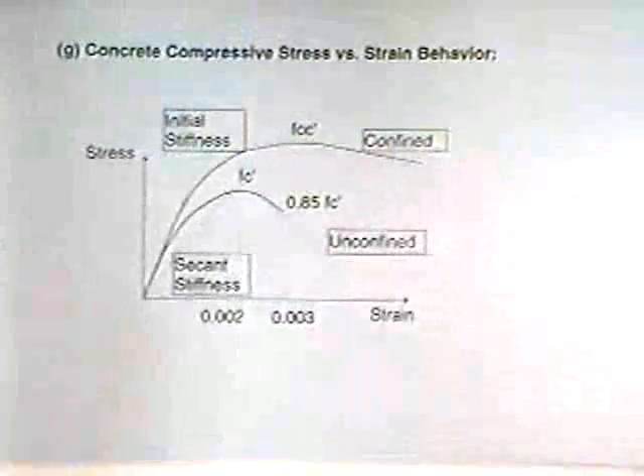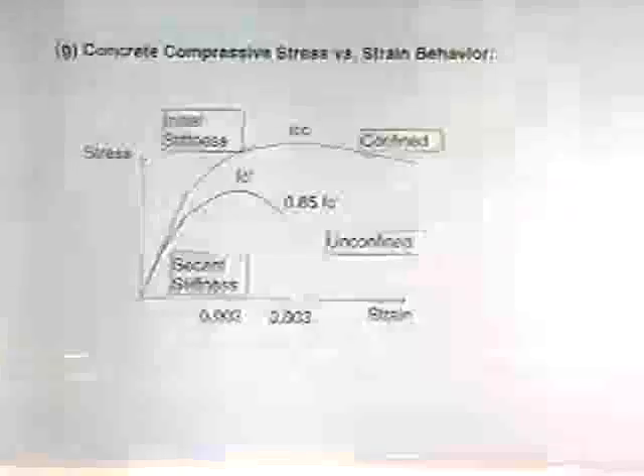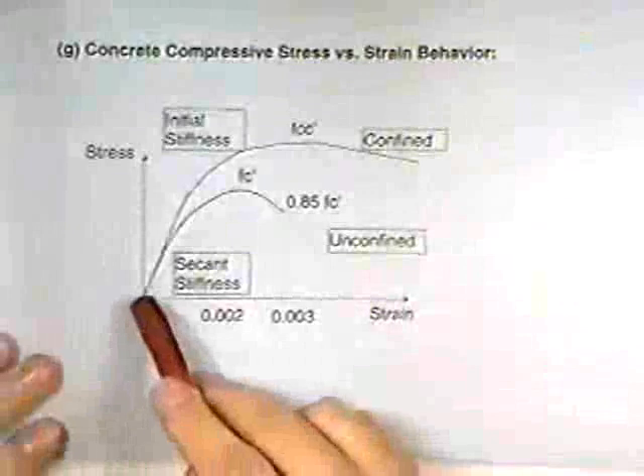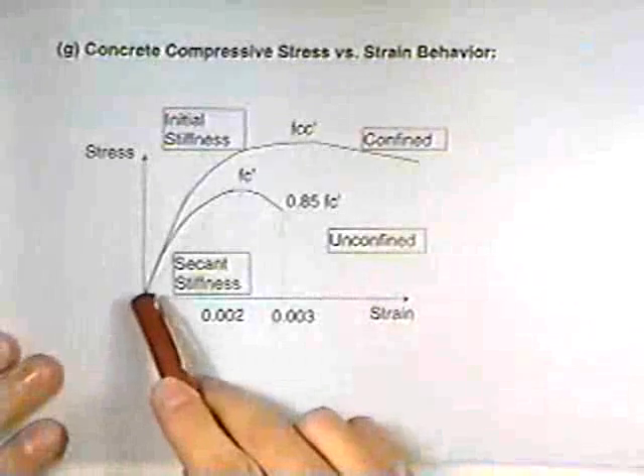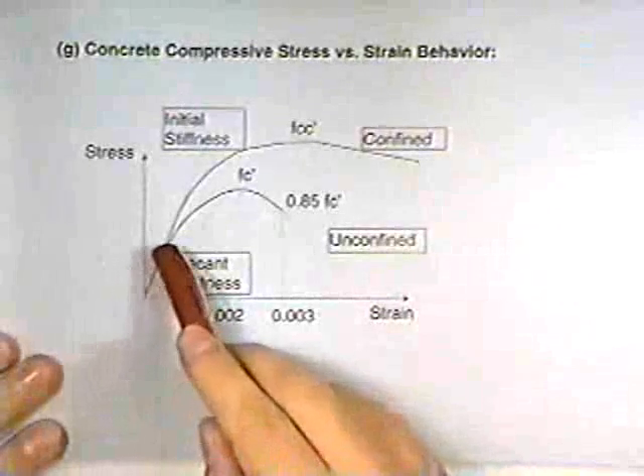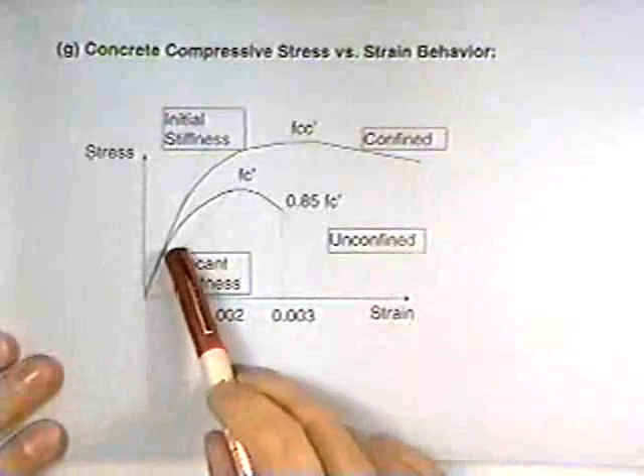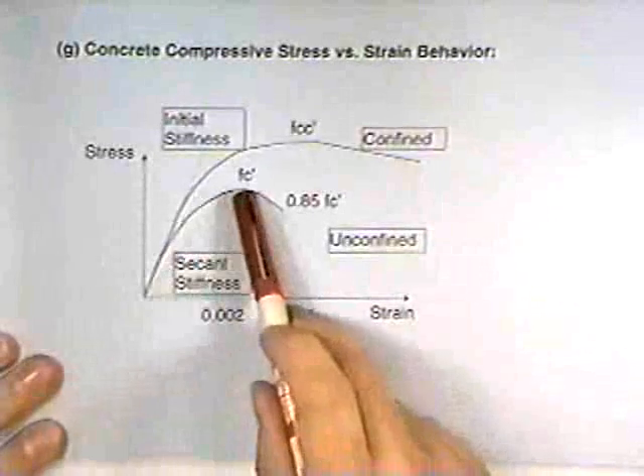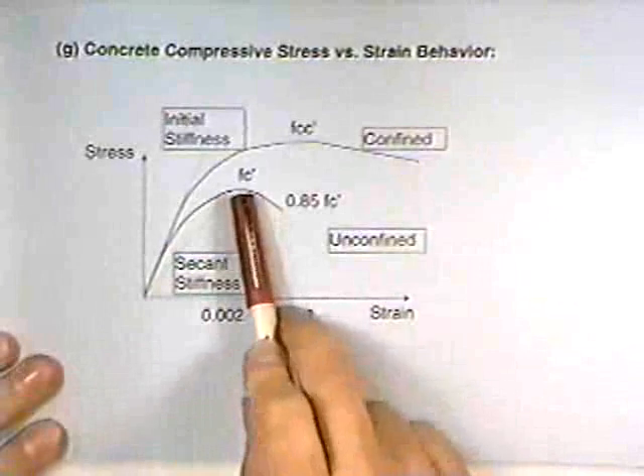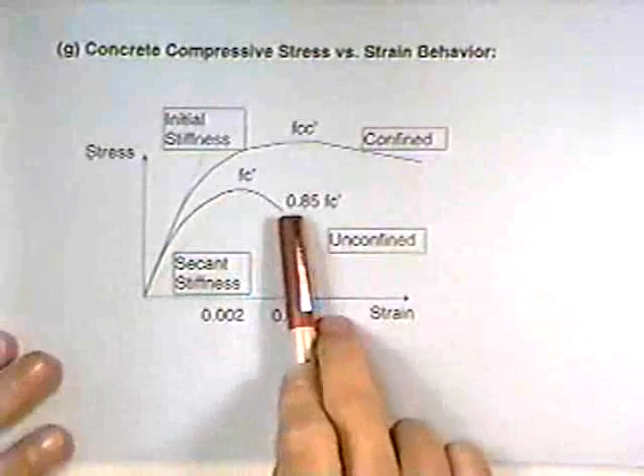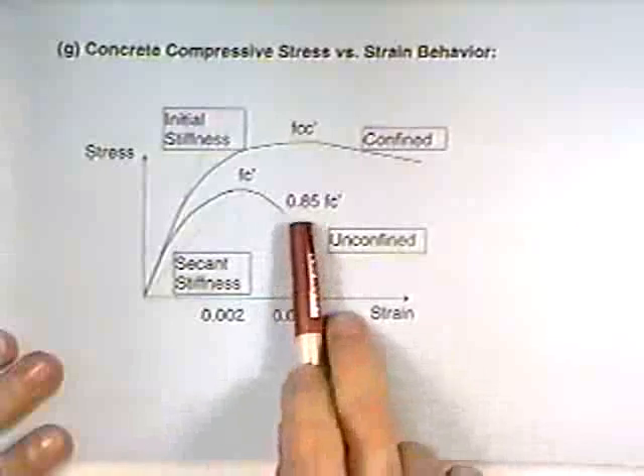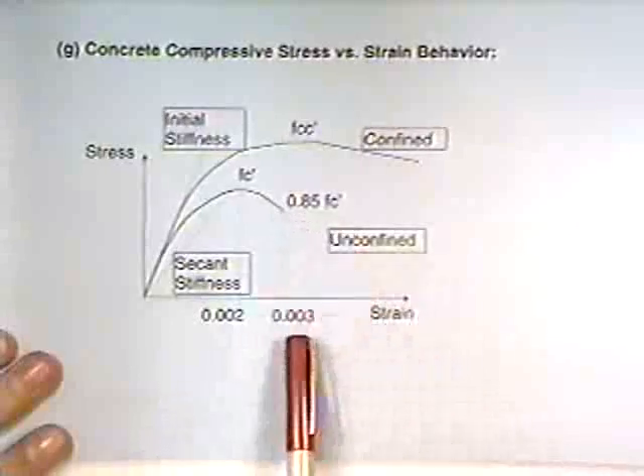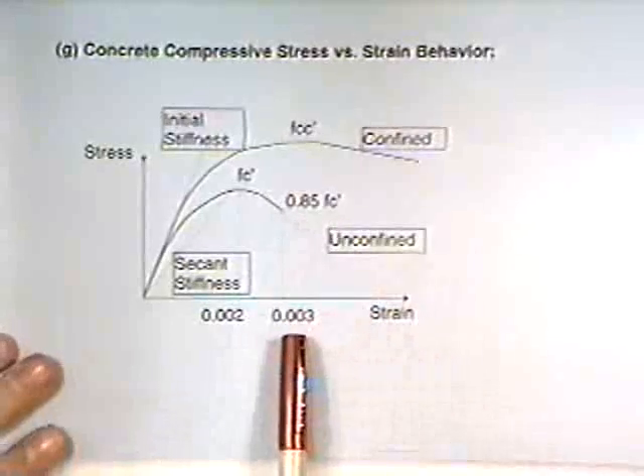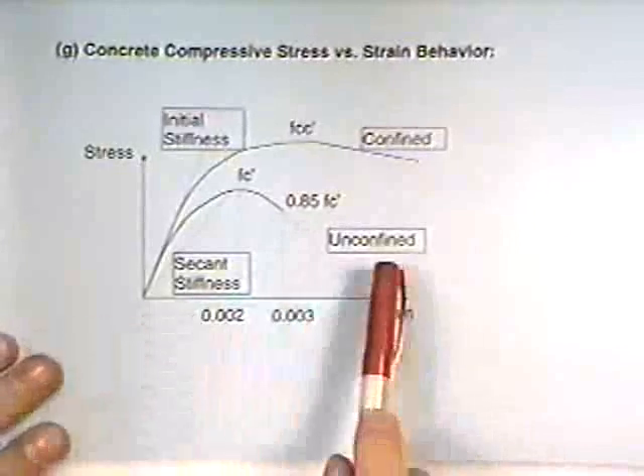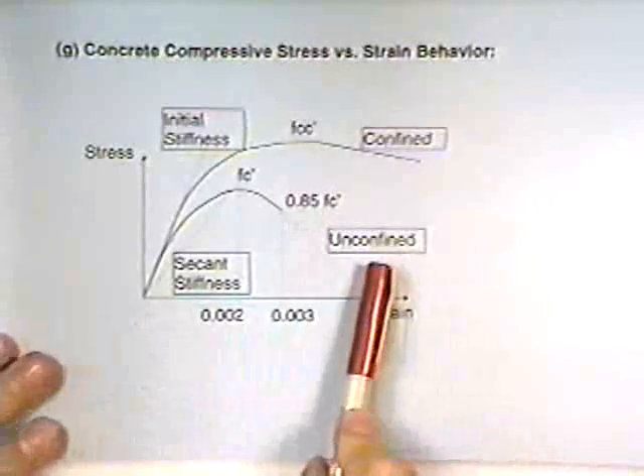Now as far as the stress strain behavior goes, for concrete we know it's very brittle if it's unreinforced. And typically what happens is that as you load your specimen in compression, it begins to deviate off the linear line at about 30% of f'c, and you get this nonlinear behavior up to its peak strength, which we call f'c. It begins to degrade, and that number then becomes 0.85 f'c at a strain of about 0.003. This is how the current code is based, and this is based on unconfined concrete.